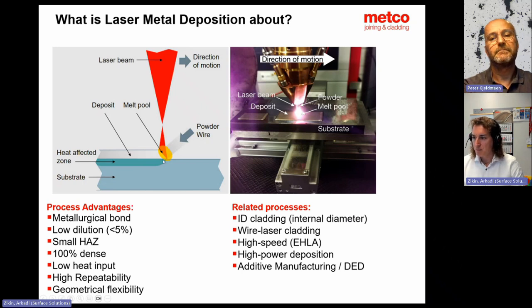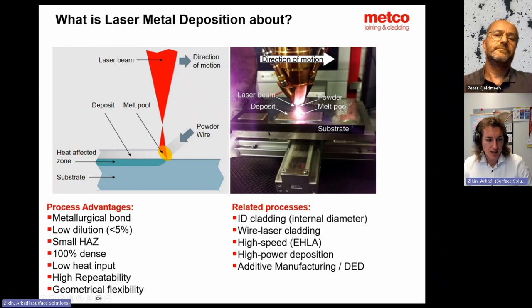With laser, by energy input control, we simplify the system, and even with thin layers, and by thin I mean 100 microns, we are able to protect the surface of your materials. So at the end of the day, you can save costs, also for post-machining, because your surface after laser cladding looks filigree. And this is also an important topic. One of the drivers behind it is related, for example, to the brake disc process.